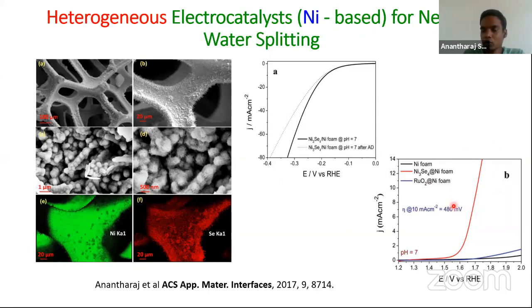You can see the ruthenium oxide, which is known for its very high activity for OER in acidic condition, and somehow still good activity for alkaline OER, is not active in pH 7. So that's why we need to search for electrocatalysts which can perform water oxidation in neutral and near neutral waters. So this is one of our results, where we found an electrocatalyst such as nickel selenide, which does not have any common ion with that of electrolyte, can also perform OER efficiently.